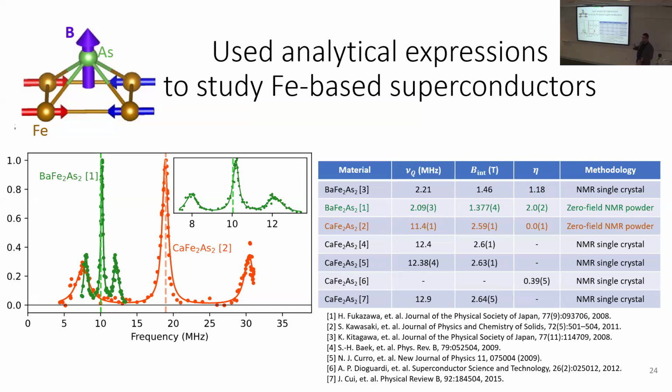When you introduce an external magnetic field, you complicate the Hamiltonian, especially because the quadrupolar Hamiltonian and the Zeeman Hamiltonian don't commute with each other. To extract all three parameters, they have to find the NMR transition frequencies as a function of rotation angle with respect to that magnetic field, so they need a whole set of these spectra.